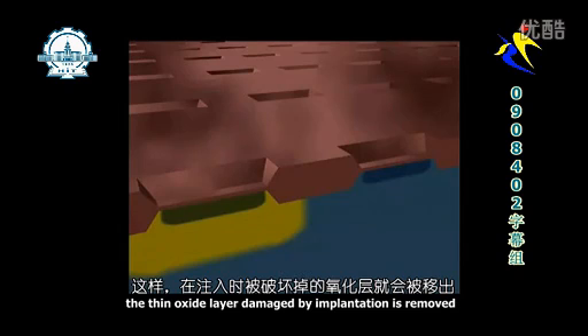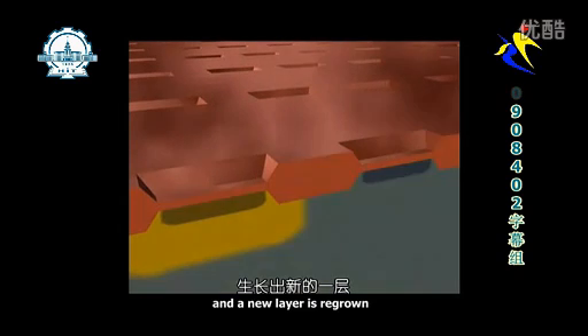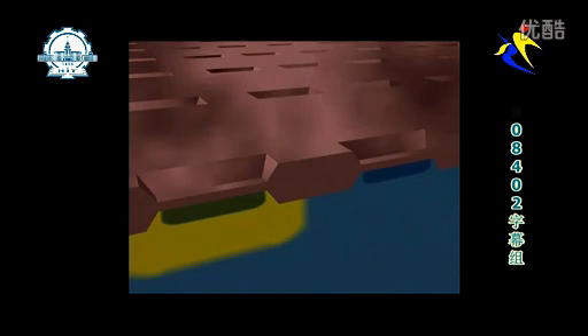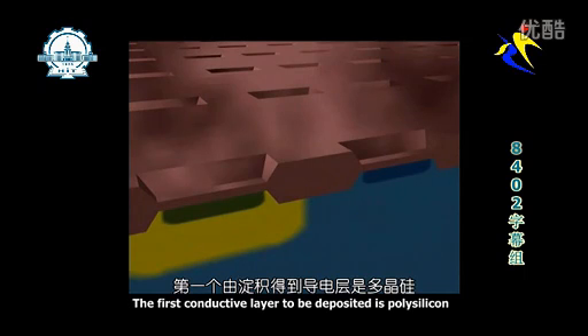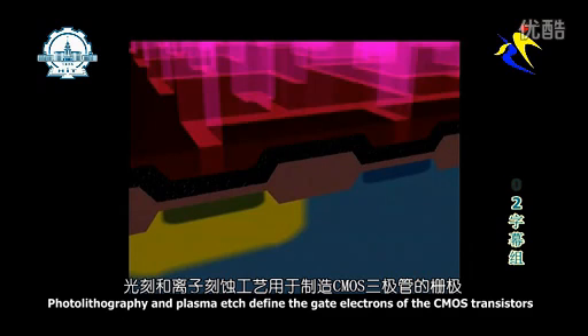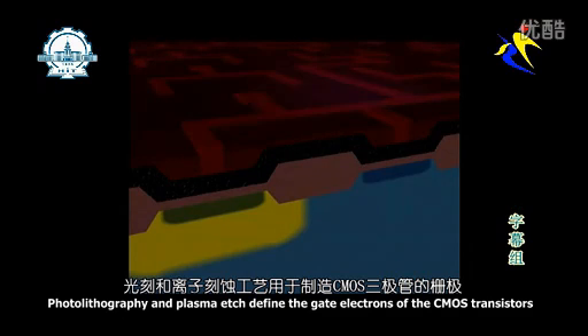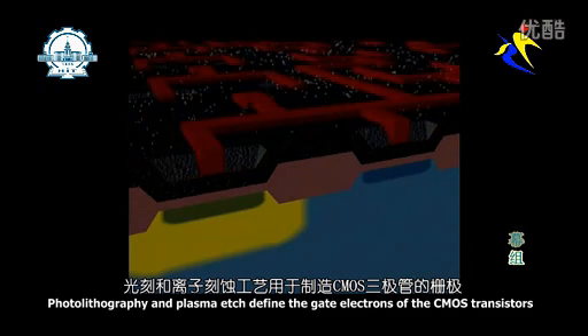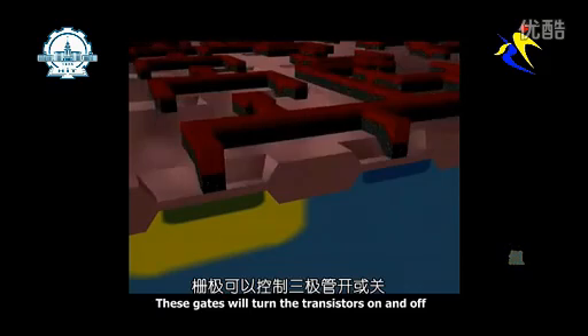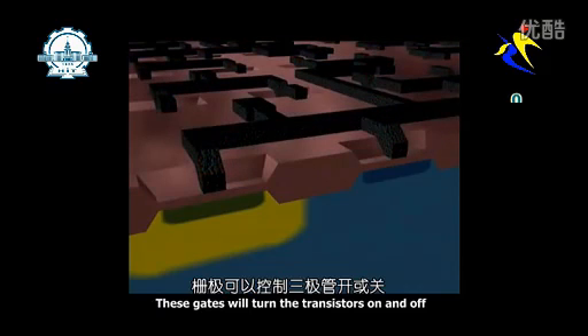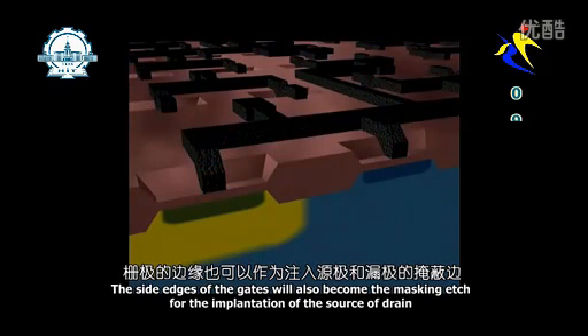The thin oxide layer damaged by implantation is removed, and a new layer is regrown. The first conductive layer to be deposited is polysilicon. Photolithography and plasma etch define the gate electrodes of the CMOS transistors. These gates will turn the transistors on and off. The side edges of the gates will also become the masking edge for the implantation of the source and drain.